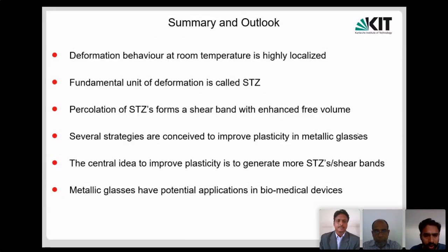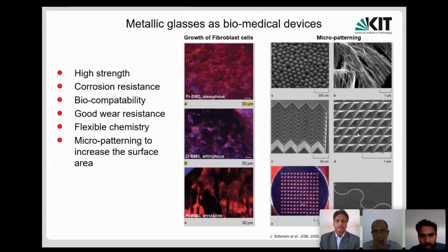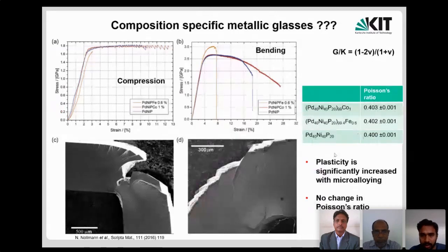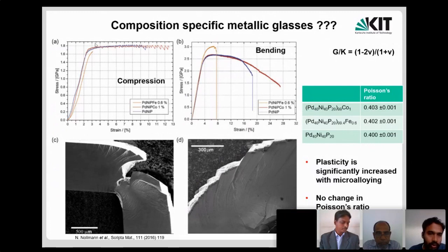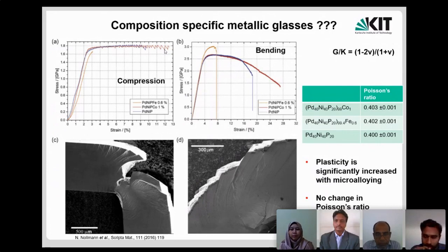It can improve. It can also degrade. It can happen both ways. If you look at this slide, they have done microalloying only here. So the glass is palladium nickel phosphorus, and they have added very little of iron, 0.6 atomic percent, and they also added like 1 atomic percent of cobalt here. And if you see the compression behavior, without any microalloying, the glass, the blue curve, shows some plasticity already. But with some microalloying with iron, the plasticity has come down drastically. But with cobalt, if you see, again, plasticity has improved. So there is no definite answer whether microalloying improves or degrades. It depends on the chemistry again.